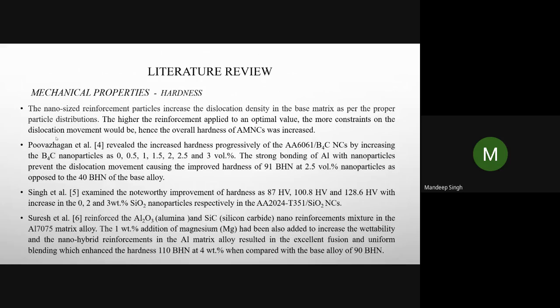Okay. So the nano-sized reinforcement increases the dislocation density in the base matrix as per the proper particle size distribution. The higher the reinforcement applied up to an optimal value, the more constraints on the dislocation movement there would be. Hence, the overall hardness of AMNC will increase. So Poovazhagan et al. revealed the progressively increased hardness of the AA6061-B4C nanocomposites by increasing the nanoparticle volume percentage as 0, 0.5, 1, 1.5, 2, 2.5, and 3. The strong bonding of aluminium with the boron carbide nanoparticle prevents the dislocation movement, causing the improved hardness of 91 BHN, Brinell hardness, at 2.5 volume percent nanoparticle as opposed to the 40 BHN of the base alloy.